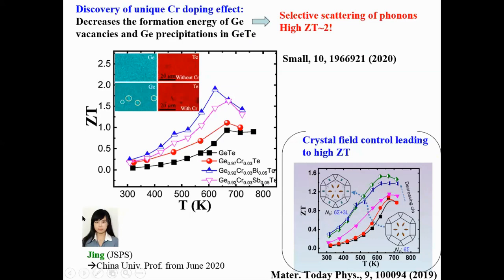And a recent result by a very recently departed postdoc, Jing. She worked on this germanium telluride material and found a unique chromium doping effect, where the chromium doping lowered the vacancy formation energy and created many vacancies, and many precipitates in the material, which were also very effective to selectively scatter the phonon and lead to this ZT of 2. So some nice results in the phonon scattering, selective scattering, the nanostructuring part.